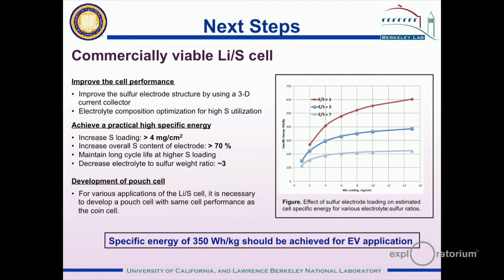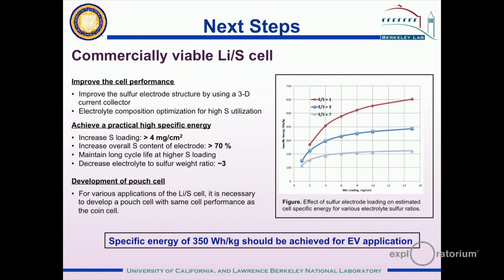And this plot shows the importance of increasing the sulfur loading up to more than 4 and maybe as high as 10 milligrams per square centimeter. And it shows the importance of reducing the amount of electrolyte in the cell. We are already in the range of 3 to 4 for electrolyte to sulfur ratios, and we may be able to go even lower. And you can see that reducing the amount of electrolyte really leads to a major increase in the amount of energy that you can store in the cell.